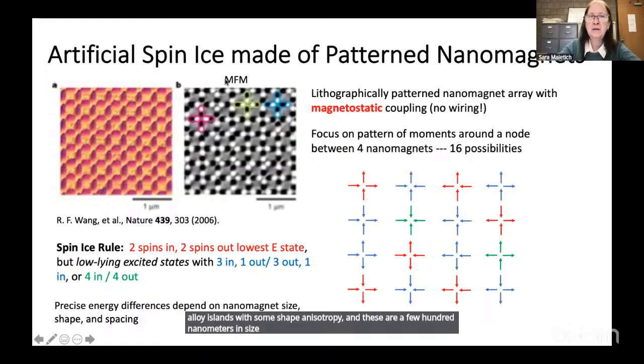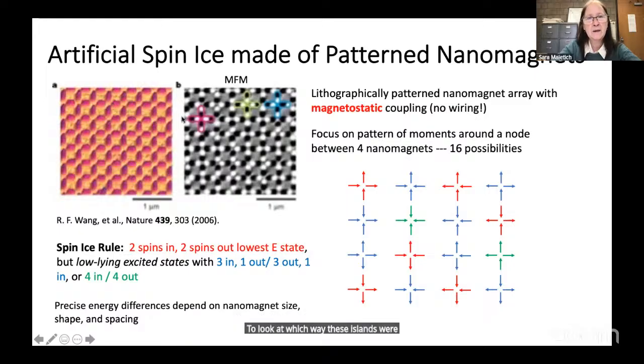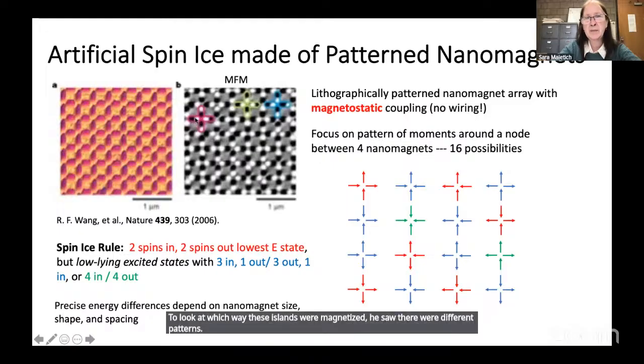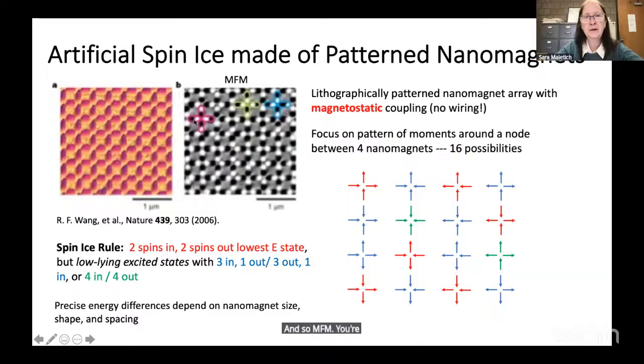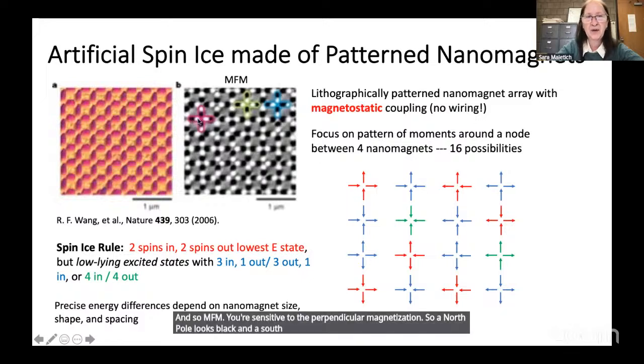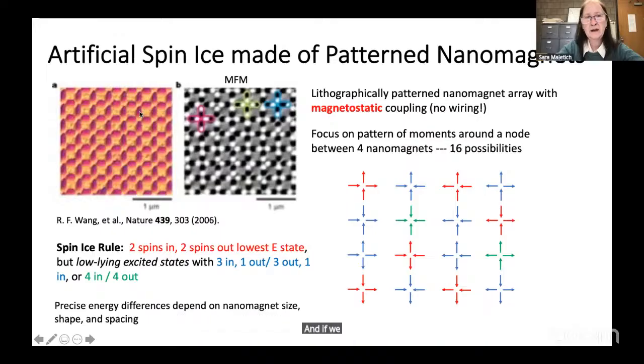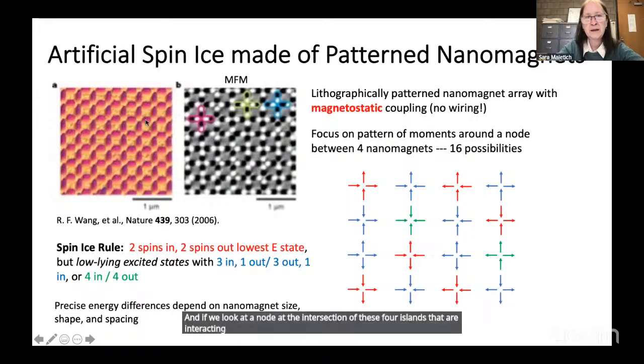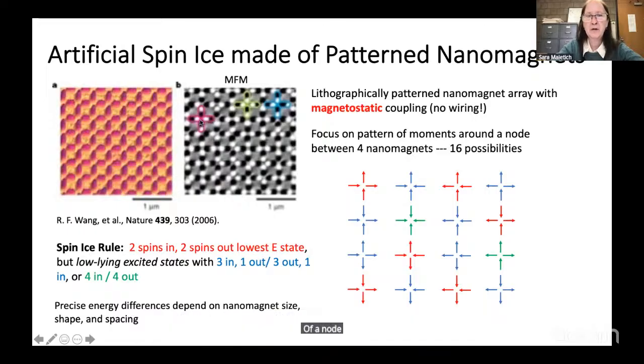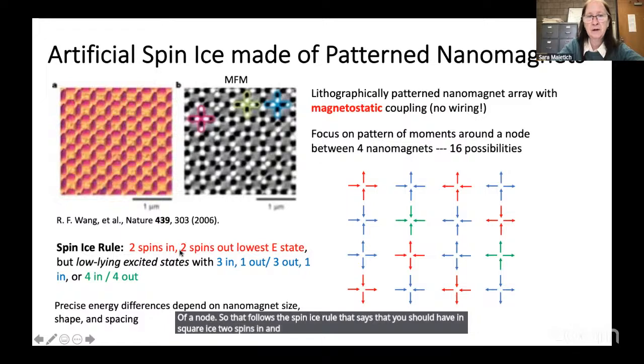But if he did magnetic force microscopy to look at which way these islands were magnetized, he saw there were different patterns. In MFM, you're sensitive to the perpendicular magnetization. So a north pole looks black and a south pole looks white, or vice versa. And if we look at a node at the intersection of these 4 islands that are interacting only through magnetostatics, we see that there's 2, say, north poles pointing in and 2 north poles pointing out of a node. So that follows the spin ice rule that says that you should have in square ice 2 spins in and 2 spins out for the lowest energy.